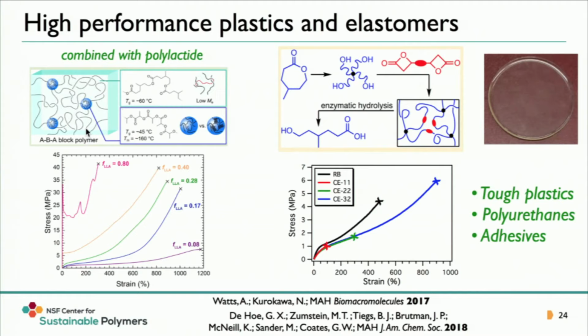And we know we can do that in Derek's system, and we know that we can do it quite efficiently. What Guillaume Dehaut did in my group in collaboration with folks from ETH in Zurich and with Professor Coates' group is we're able to make now cross-linked elastomers using methyl caprolactone. Now this is a picture of one. You can think about these as quite stretchy, resilient materials. In fact, their mechanical properties, which are shown down here, are quite comparable to something like a rubber band. And that black curve here is for a rubber band. And we're able to make these really high-performing elastomers by using a new cross-linking agent that came out of Professor Coates' group and our methyl caprolactone materials.